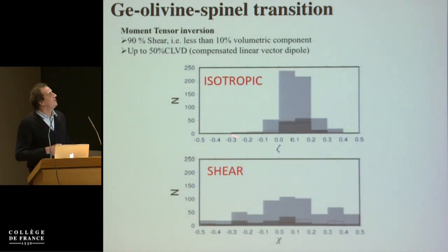So what Lupe also did was the moment tensor inversion, actually not focal mechanism. And so he measured the isotropic and shear components. And most of the events have a very small isotropic component, let's say around 0, between minus 0.1 and 0.1. And we have a very large possible CLVD component where we go from minus 0.5 to 0.5. So our events are still in shear. So this is also something that they share with the real deep focus earthquakes.